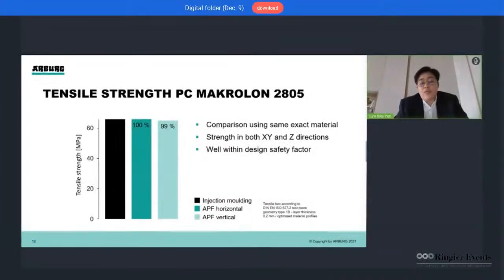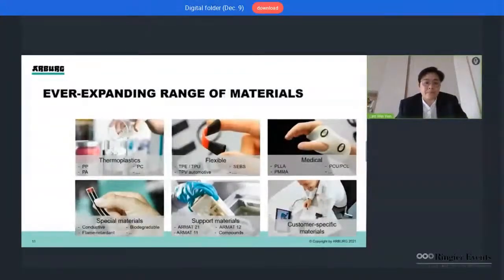Results can vary with different materials, but this result is based on polycarbonate PC, and we can see that the results are generally very close to injection molding. We are reaching about 99 to 100% in both directions. The unique combination of processing pellets with this droplet discharge and the nozzle closure system allows us to cover a wide range of material properties.